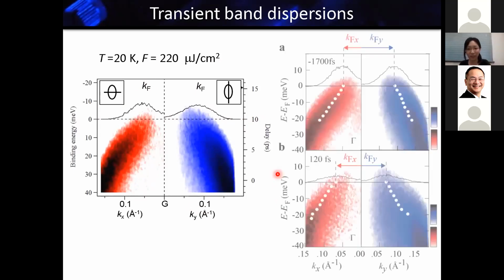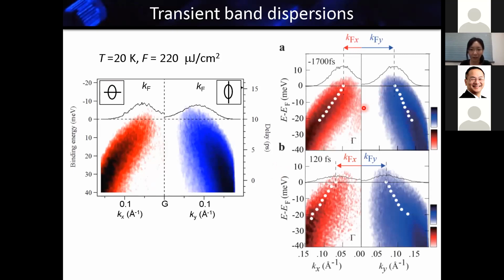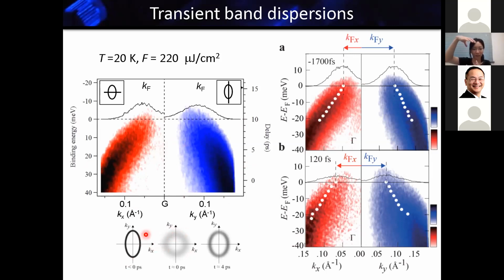I don't know if it's moving, but let me pick up two images at two times. This is the image before pumping, the kind of ground state. At first, kfx and kfy, the short kf and long kf, are quite different. But this is 120 femtoseconds, just at the pumping, and it becomes equivalent. It means that the Fermi surface becomes completely circular when it's pumped. This movie shows that the elliptical Fermi surface first goes to circular, and then moves back to the elliptical shape again.